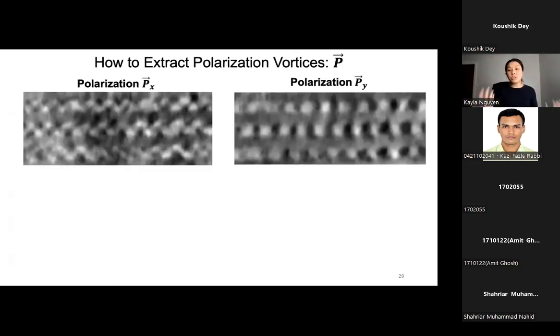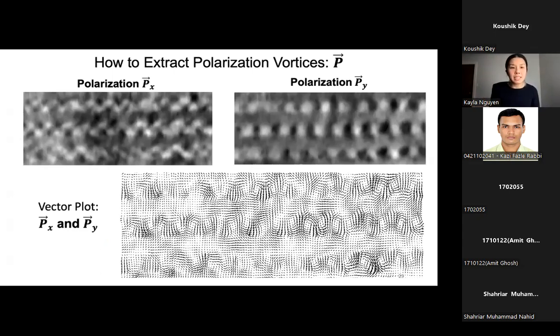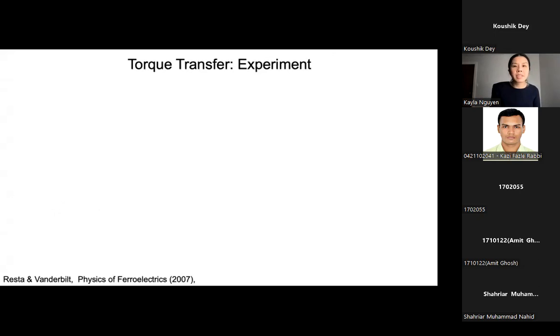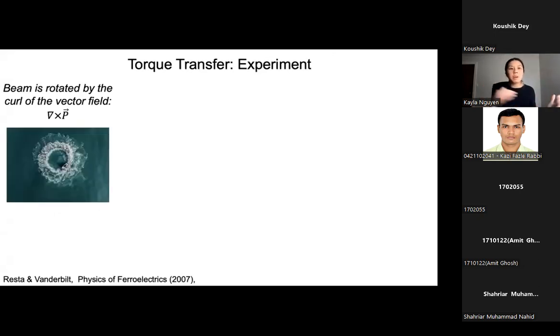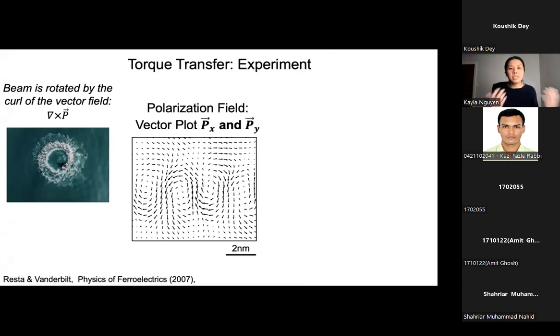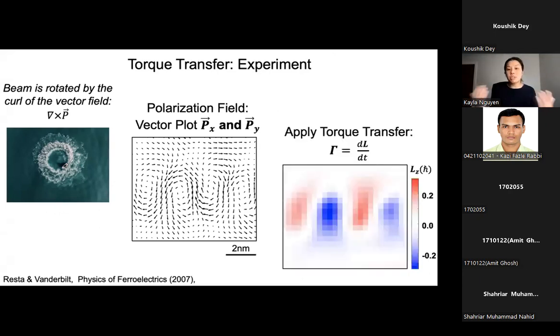Now you have these two vector components of polarization, in X and Y, and you can reconstruct these vector plots and get back your information related to the polarization vortices simply by looking at the asymmetry of your conjugate pairs of diffraction disks. All right, so now that you have your polarization information, how do you get back torque transfer? Because the beam is rotated by the curl of the vector field, all you need to do is take the curl of your polarization field, which you know here, and then you can apply the torque transfer technique, or the equation that I showed you in one of the beginning slides.